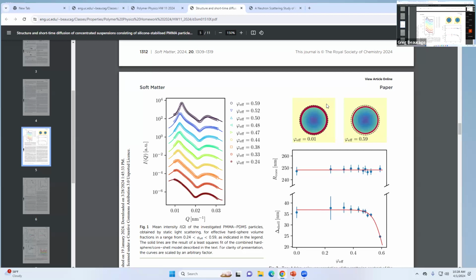So this whole model of having these surfactant-modified particles that allows it to be a colloid is really weird. The whole thing doesn't make that much sense, actually. It wouldn't suspend in that case. These things would just cluster together and then precipitate out, because the soluble PMMA would never see the solvent since it's coated with PDMS.